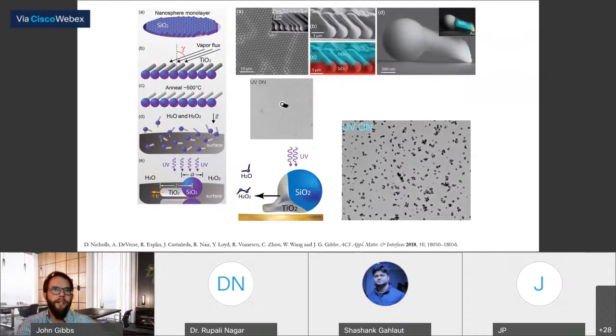But overall, it's really the same exact process as designing the spherical Janus particles as well. So tilt it to an angle, deposit quite a bit of TiO2, do the annealing process again, put them into water and H2O2, sorry. And then we are going to look at their behavior. What's kind of interesting about this is that we start to find out that the morphology, not just the material properties, the catalytic parts of the structures, but also the morphology, the shape of the particles, is going to have a large influence on the way that they move and self-assemble.